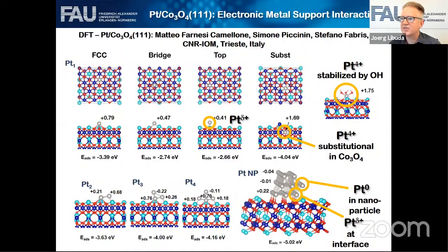And I don't want to discuss all the details in here, but I just want to point out two things that are important. So one thing that you learn is if you have platinum atoms that are in direct contact with the cobalt oxide, the electronic structure changes. Typically, you have partial oxidation of the platinum. We call that an electronic metal support interaction. If you have larger particles, the platinum in the second and third layer is already something like metallic platinum, platinum zero. So that's electronically different.